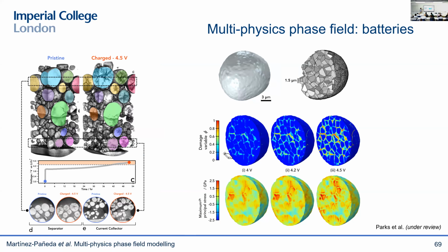And we have also taken this even one step further, again building on these nice imaging facilities that these people have. We're looking into the microstructure of the particles, and we can see grain boundaries. We're simulating grain boundary cracking as they observe in the experiments, to be able to further understand how the cracks develop in these electrode particles, and what would be the benefit of having single crystal electrode particles, which is now what everyone thinks will be a big difference in improving battery performance.